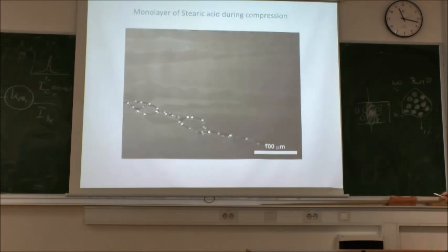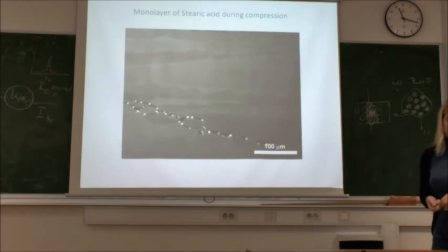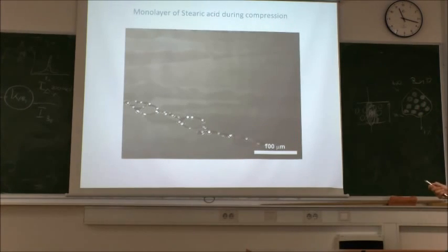We can also observe these interesting zigzag patterns, which indicate that the tail chains of the molecules are not oriented perpendicular to the surface, but instead they are tilted in arbitrary directions. In the solid phase, these patterns and also domains should disappear, but I don't have any pictures of the condensed phase.